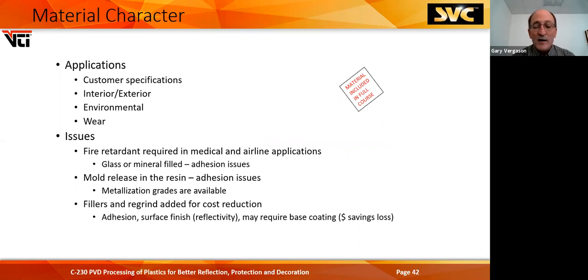A lot of your fire retardant materials are in medical and airline applications. Mold release is in the resin, and with metallization grades, you have very few adhesion problems with those materials. Fillers and